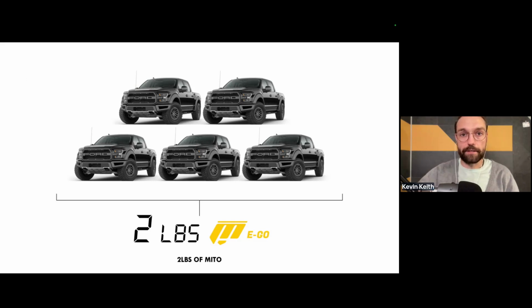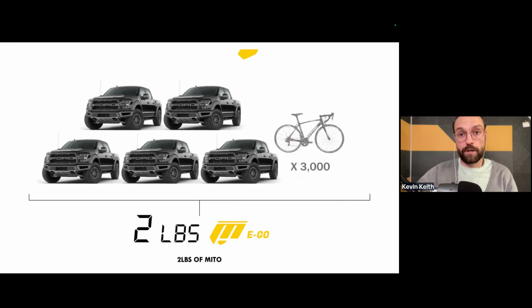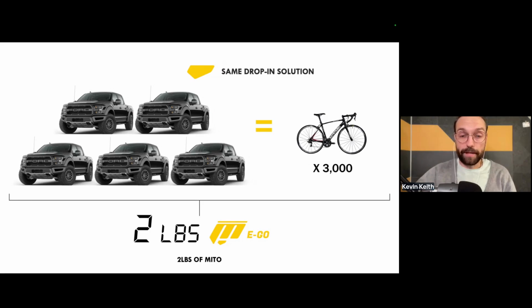To give you an idea of the impact of graphene materials, we have a functionalized product called Mito Ego that at 0.1% by weight loading, it can make products up to 100% stronger or up to 35% lighter. And what that really means is that with 2 pounds of this material, you're able to lightweight enough plastic in 5 Ford F-150s by 35%, or increase the strength of 3,000 carbon fiber bike frames by 100% with the same drop-in solution. That's because we tailored the functionality of this system to be polymerically compatible and easily dispersed into a wide range of materials.